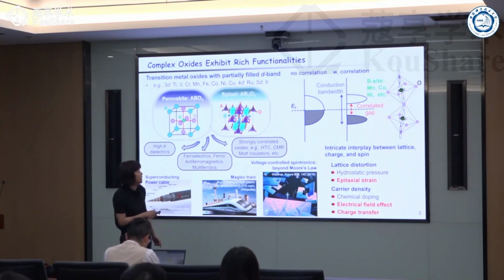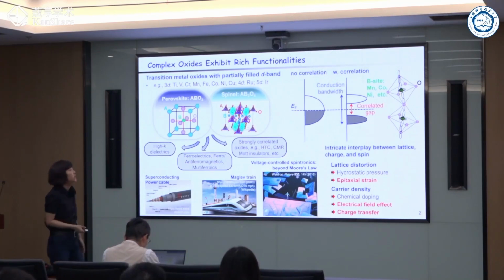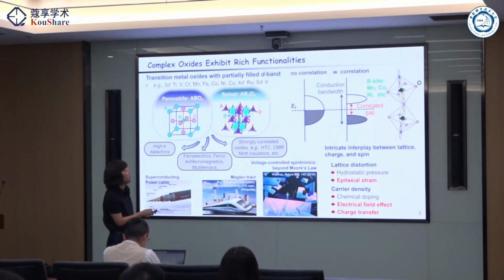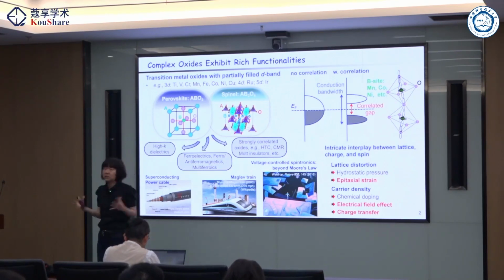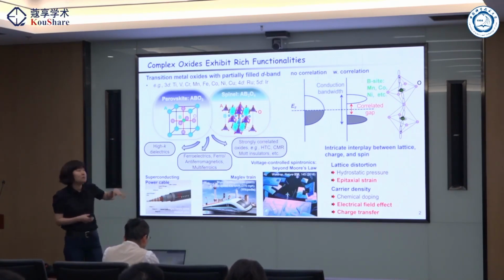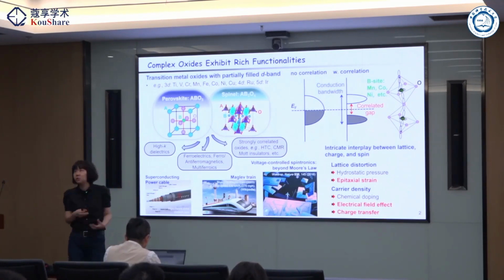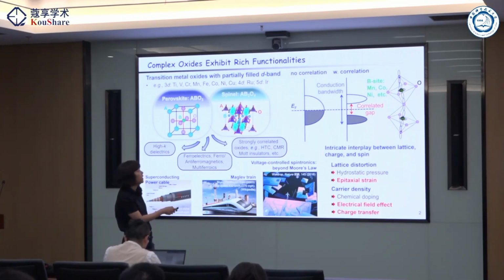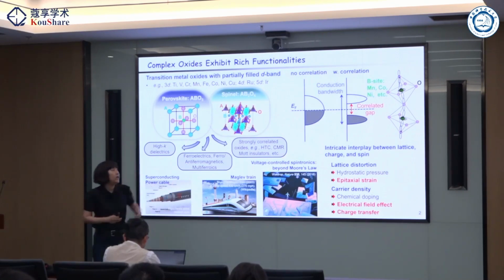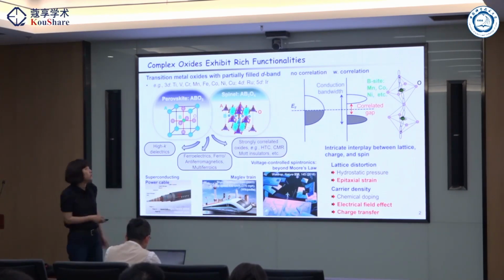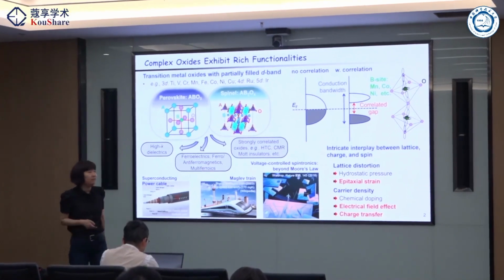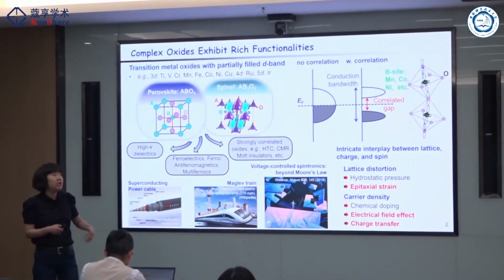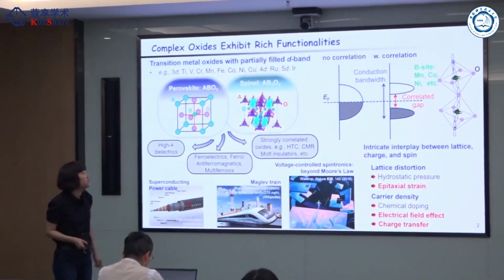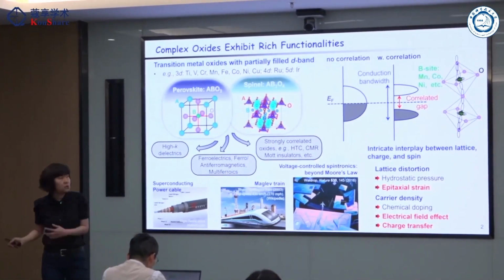I will use a perovskite as an example. So I have this cube, and the B-site cation is surrounded by an oxygen octahedron. If the cation is too small, I cannot sustain a perfect cube, and the oxygen octahedra would tilt or rotate. So this will bend the cation-oxygen-cation angle from 180 degrees. And that will reduce the electronic bandwidth as well as change the magnetic exchange. So that changes it from a metal to an insulator and changes from possibly a ferromagnetic state to an antiferromagnetic state.